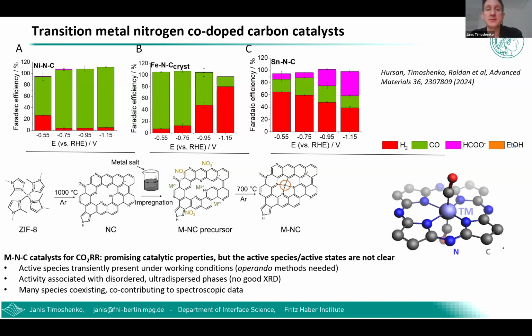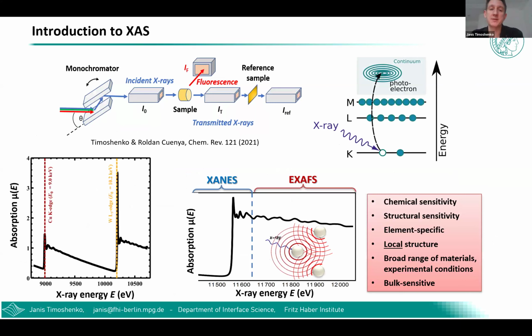But if you want to understand how these catalysts adapt to reaction conditions, how can we do it experimentally? For that, we actually don't have many different techniques available, because these catalysts are so small that you cannot really see them in a microscope, or even in an electron microscope under operando conditions. They also don't produce any X-ray diffraction peaks. So basically, almost the only technique which you can use for this purpose is X-ray absorption spectroscopy, which for us is very nice because this technique is very close to our hearts.